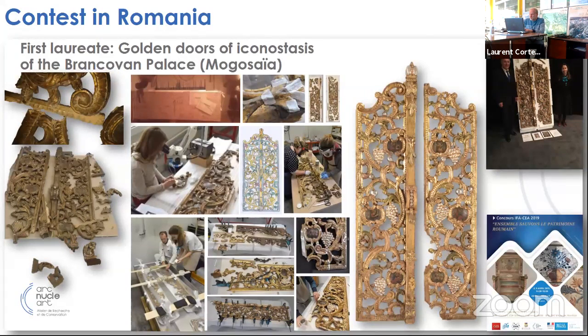So finally, a conventional weak consolidation using acrylic resin in solvent was done from the back. It was just enough to allow the cleaning of the last paint layers. Then the reassembly was done at maximum. Of course, the doors cannot stand up by themselves because the consolidation is too weak. But I think that the result is very interesting.